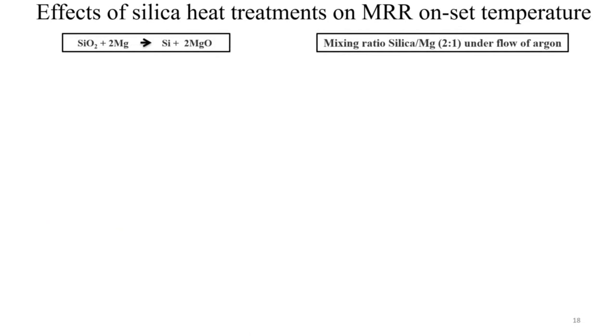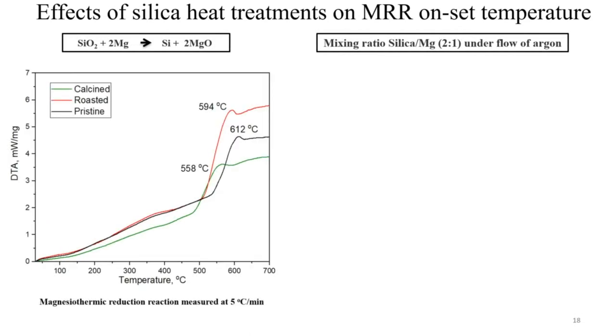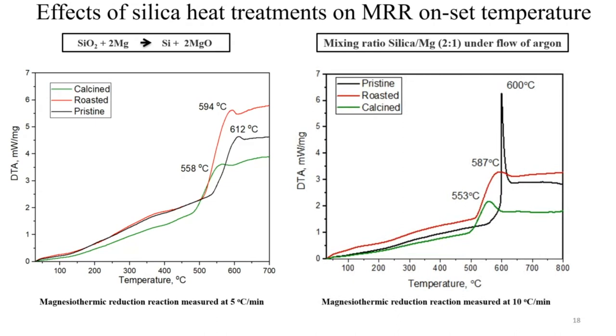This part of the study focused on the effect of heat treatment on the onset and peak exothermic temperatures of different silica precursors on the magnesiothermic reduction. And as can be seen here, this particular measurement was done under two different heating rates, one at 5 degrees per minute and also the other at 10 degrees per minute. And it was first of its kind because, I think, in existing literature, not so much work has been done to understand the effect of the crystalline structure or amorphous structure on the onset silica reduction temperature. So this particular result shows that the crystalline silica powders had a lower onset reduction temperature than the pristine, that's the amorphous silica powders.